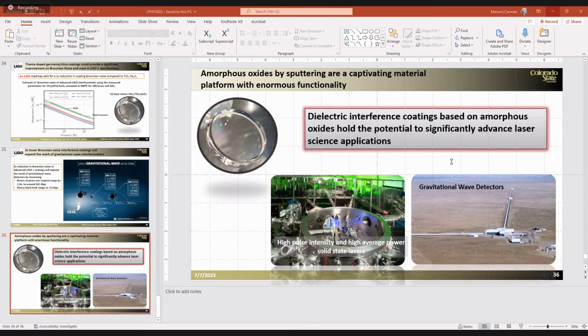So in other words, what I showed about Germania is the first time that it is shown that a film grown by sputtering can actually reach an organization that is that of a stable glass. I wouldn't say ultra stable. There is much more disorder in the sputtered thin films. So you can think, okay, they are not really glasses; they are nanoceramics.